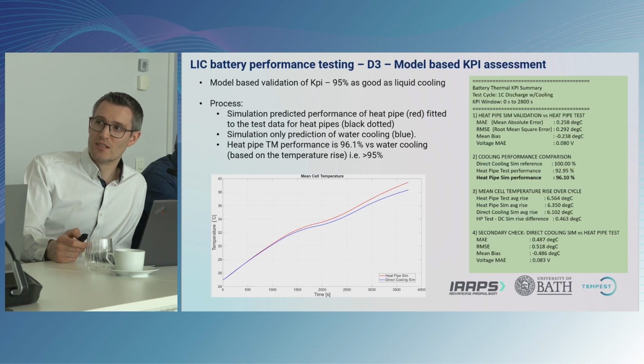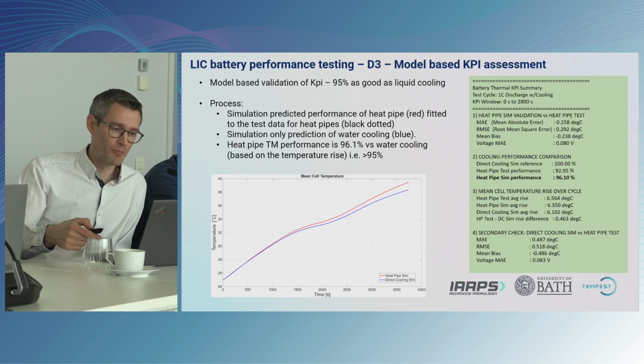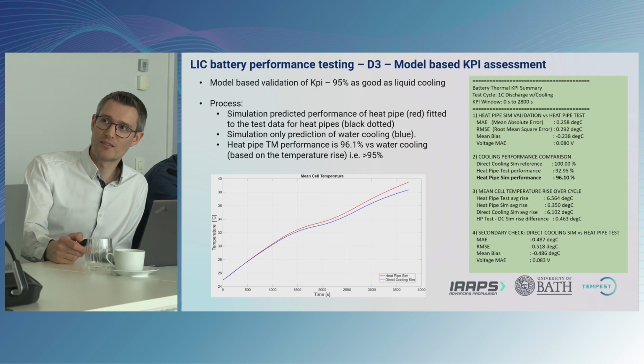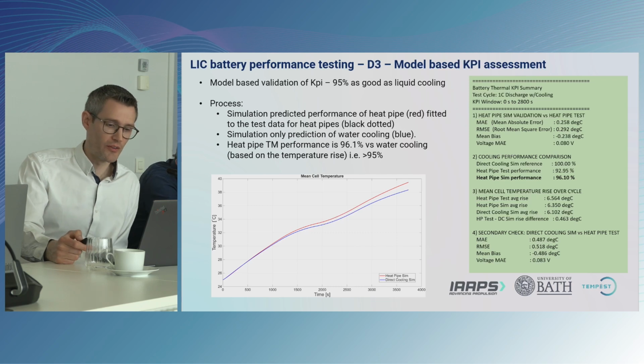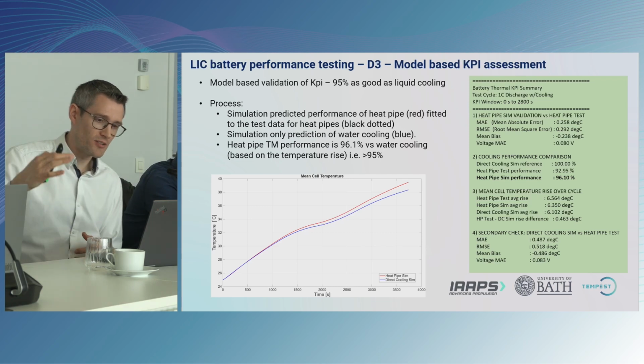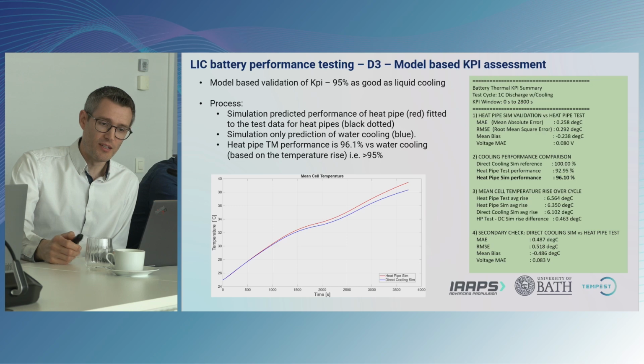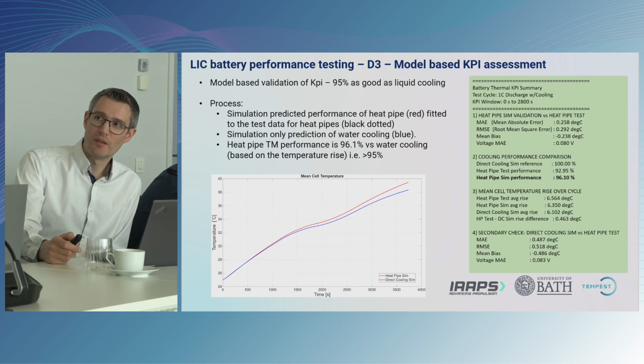The second reason is that it gives you the opportunity to completely remove the need for water cooling. So one of the other tests that we're still trying to process the results of is removing the heat from the cold plate with air cooling. So rather than taking the heat to the top of the module using the heat pipes, but then evacuating that with air cooling rather than with the water-cooled cold plate.